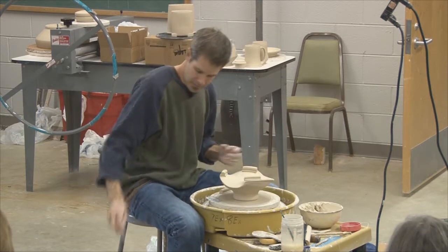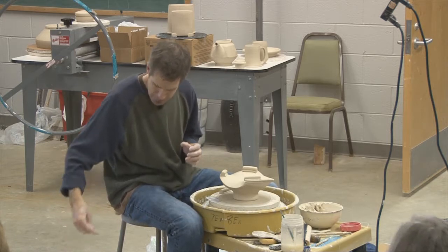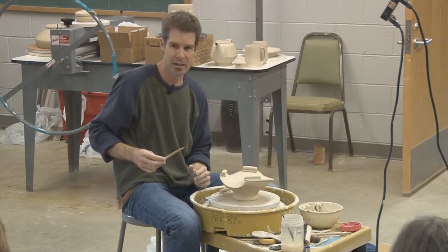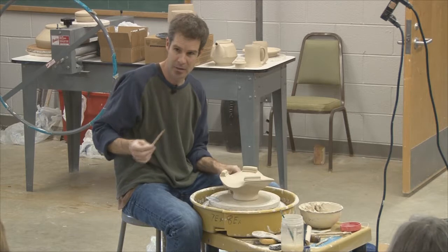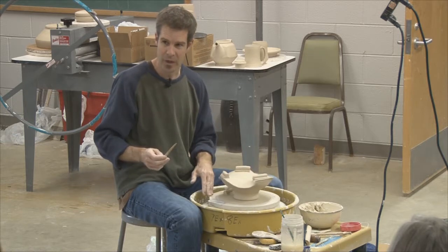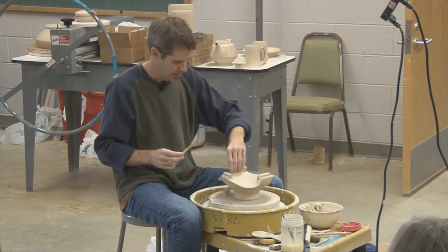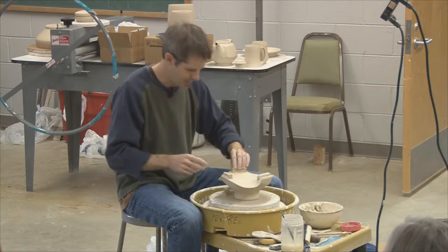At some point I figured it out. I don't know how, but I figured it out when I was at Guilford, and I started making kiln wash out of alumina hydrate and EPK. Half of the EPK was calcined, bisque fired, and half of it was just right out of the bucket. But that's been great. I haven't had any problems with that. Without having that silica in the kiln wash, it doesn't, over time, start to have pots stick to it.